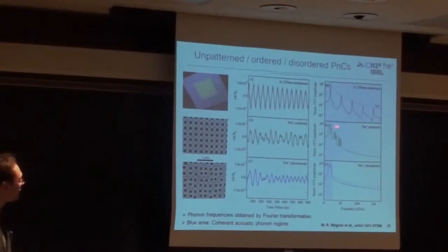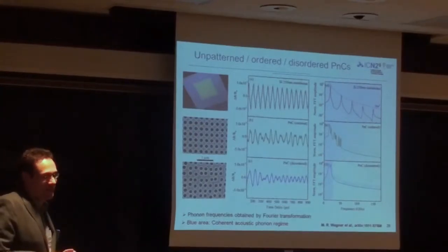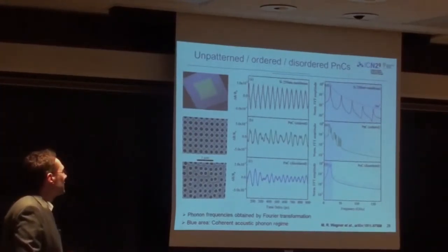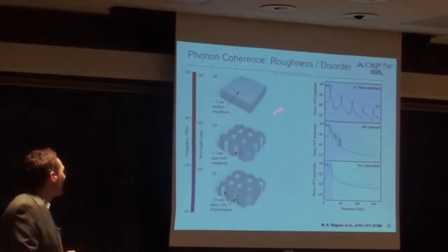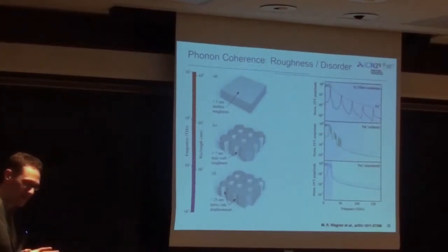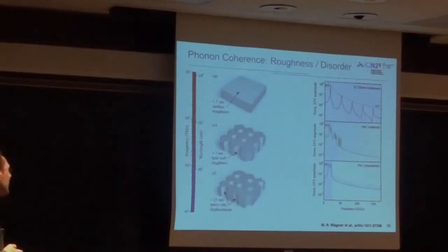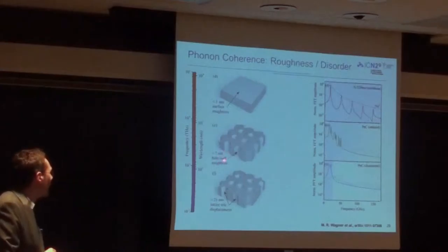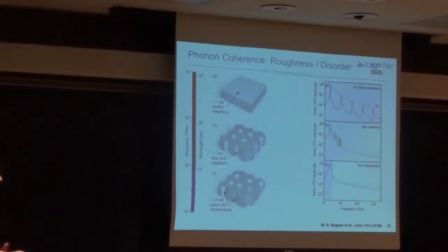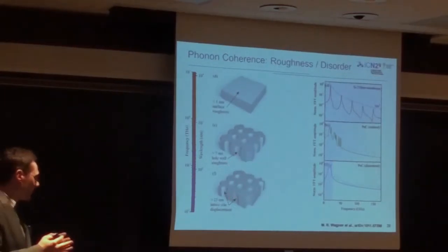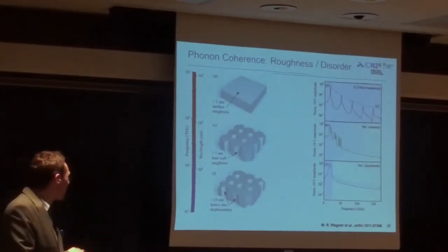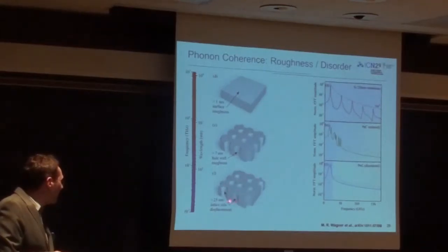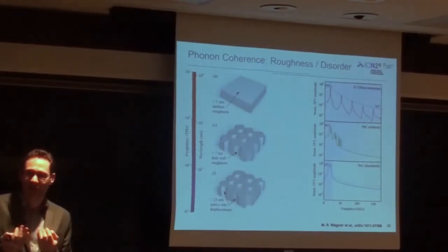And basically what is tried to indicate here is in blue is a range in which we can see this coherent acoustic phonon regime. So if we are now considering that our bare membrane has a roughness of around 1 nanometer, and if we introduce now this regular hole patterning, we also introduce a hole wall roughness due to the reactive ion etching process and so on of the range of around 7 nanometers. And then finally, the displacement, the disorder that we have in the disordered phononic crystals can be somehow considered also